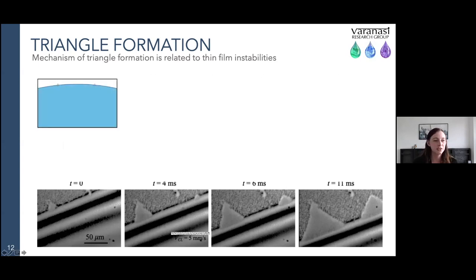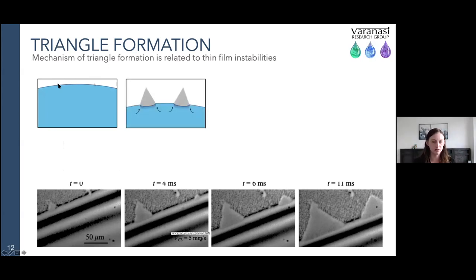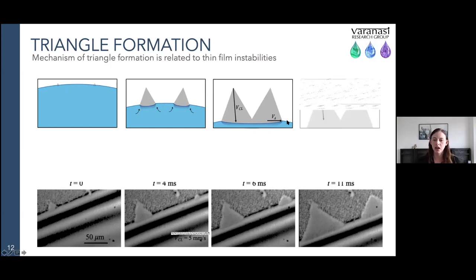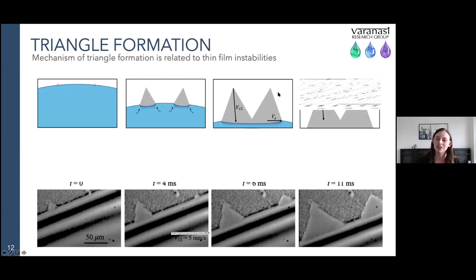Breaking this down into a cartoon: there are periodic nucleation points at the tops of the triangles as they start forming. As the contact line recedes downward, the triangles continue forming, with flow moving towards these triangular regions where the contact line at the emerging phase moves just a little bit faster than in the surrounding phase. Based on both the contact line velocity in the radial direction and an instability velocity in the axial direction, we get a variety of patterns — a wavelength between triangular peaks and a triangular angle that is a function of these two velocities.